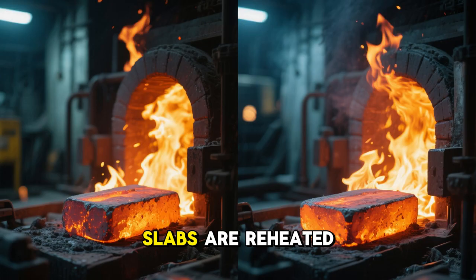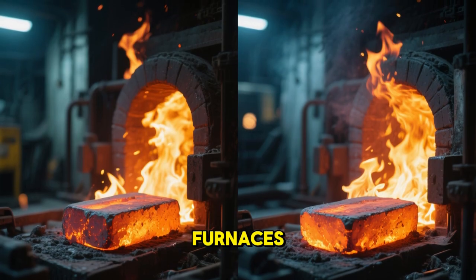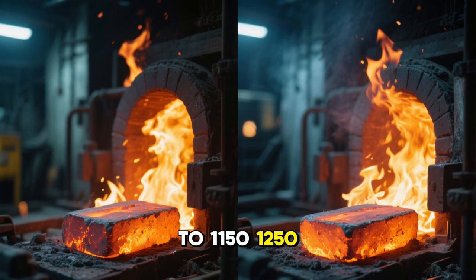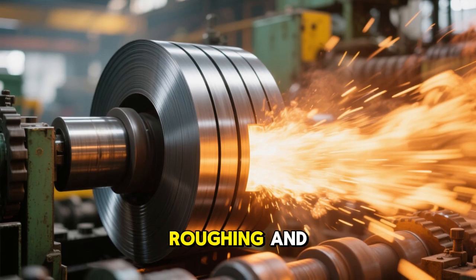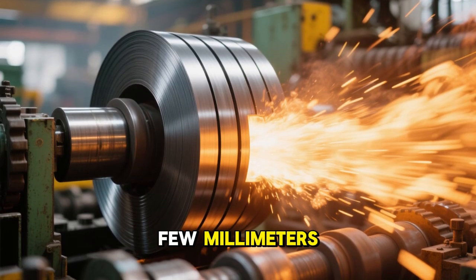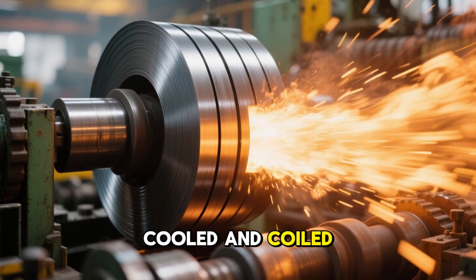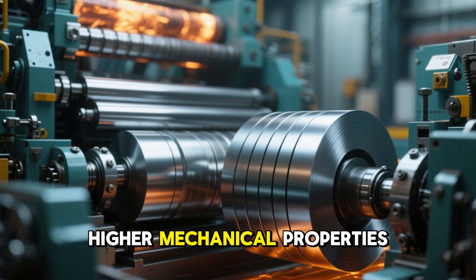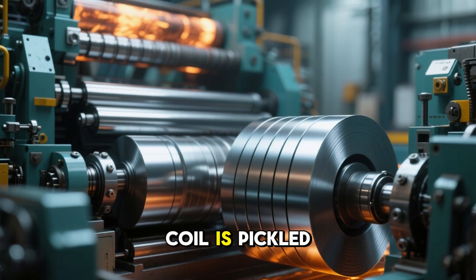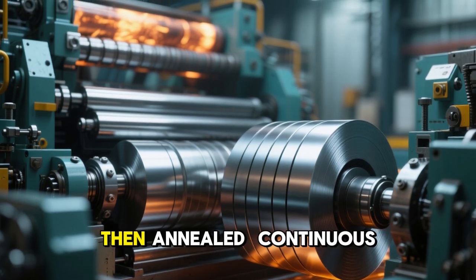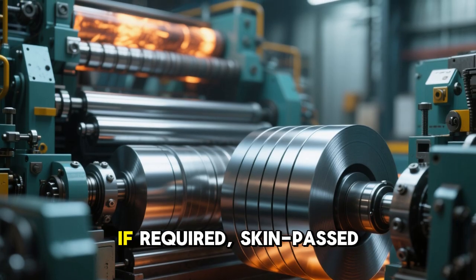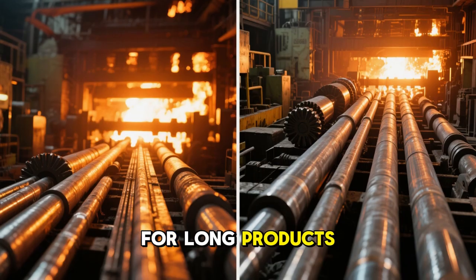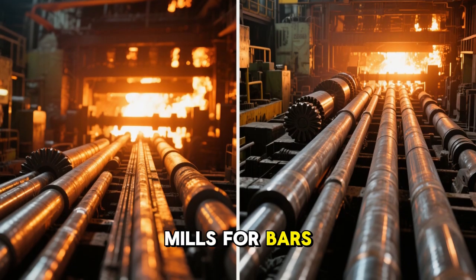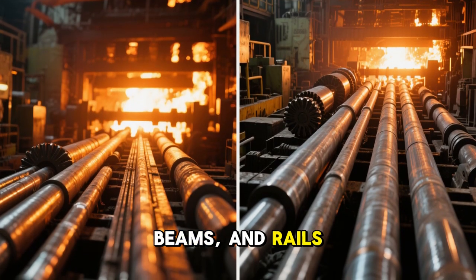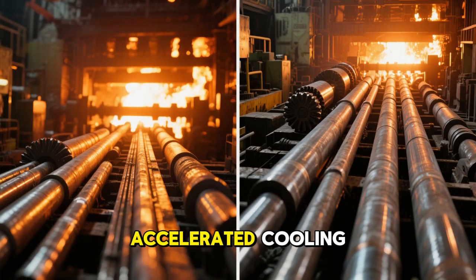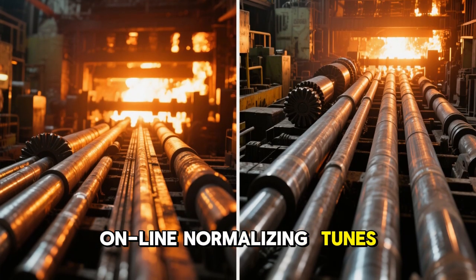For flat products, slabs are reheated in pusher or walking beam furnaces to 1150-1250°C, and hot-rolled in roughing and finishing stands down to a few millimeters. Hot strip is cooled and coiled. When tighter tolerances, better finish, and higher mechanical properties are needed, hot-rolled coil is pickled and cold-rolled in tandem mills, then annealed, continuous or batch, and if required, skin-passed. For long products, billets and blooms feed hot mills for bars, rounds, wire rod, beams, and rails. Controlled cooling on the runout, accelerated cooling, online normalizing, tunes properties.